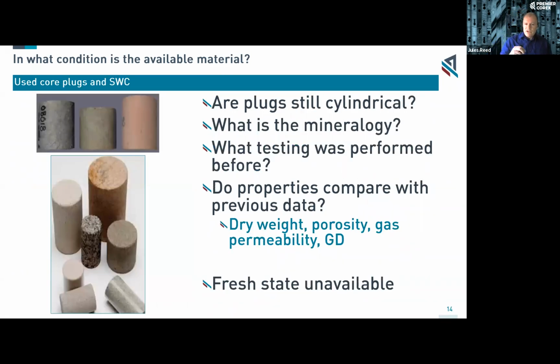The next one is the used core plugs. Now, what are the decisions we need to make about used core plugs? Well, one of the first ones is, what's the condition of the plug? Is it still intact as a cylindrical plug? Because we are going to be placing these samples into perfectly cylindrical equipment. And the more non-cylindrical, or the less integrity there is in the sample itself, the more likely that we're going to have problems like failure of the equipment, leakages through the sample, as you may get punctures through the rubber sleeve that surrounds the sample. So we have to look at the shape of the sample and the integrity of the sample.